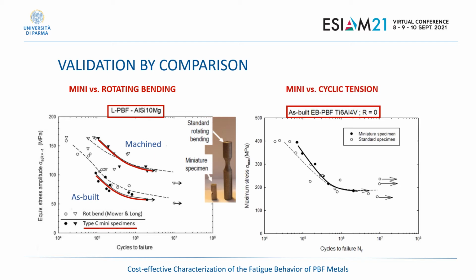We continue here with a comparison of our miniature specimen results with cyclic tension data, again from the literature. In this case, it's an electron beam produced titanium. And here again you have a good correlation between the miniature specimen data and the standard data.